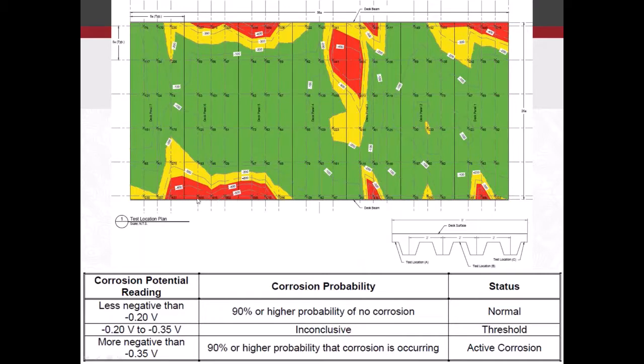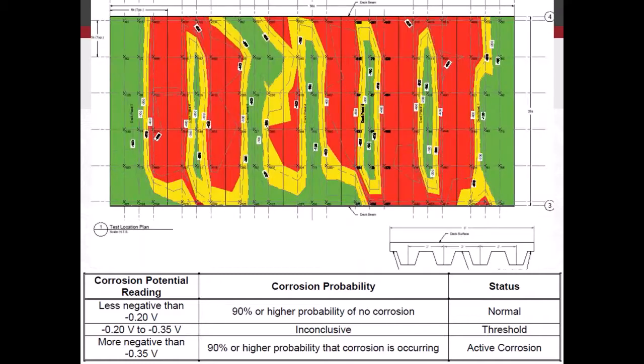And the corrosion's happening where we would think, right here, along the beams, kind of the joints, right? Water, kind of salt-laden water, melting and probably leaching into the concrete, causing some corrosion. So this is kind of one of the bays that we tested. This is the results here. And this was another bay that we tested.